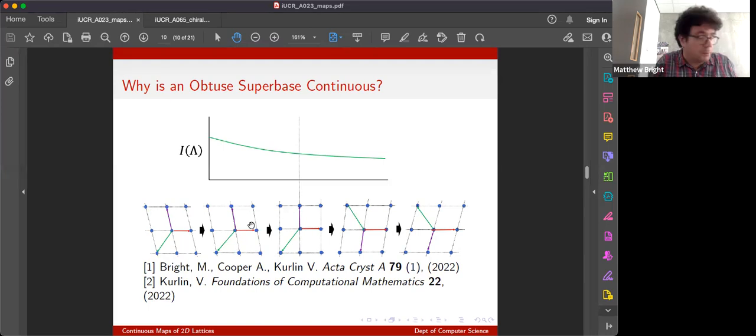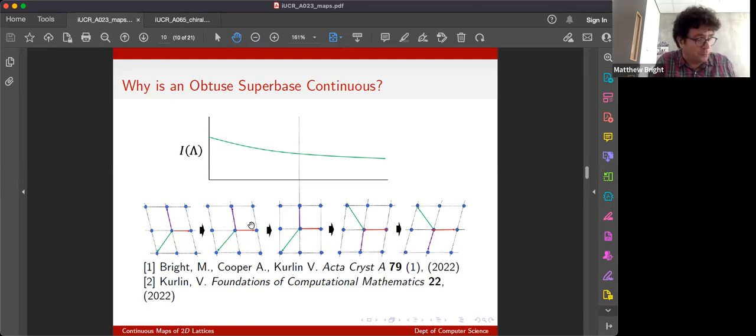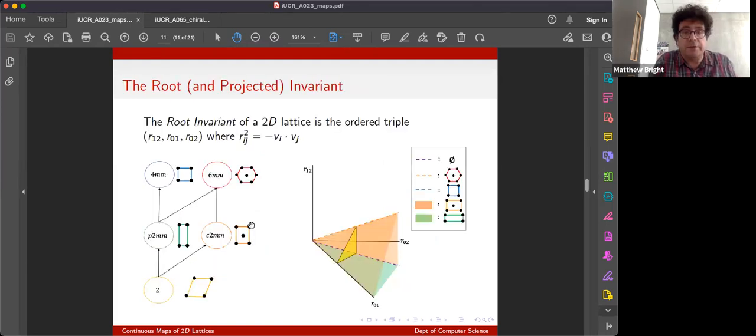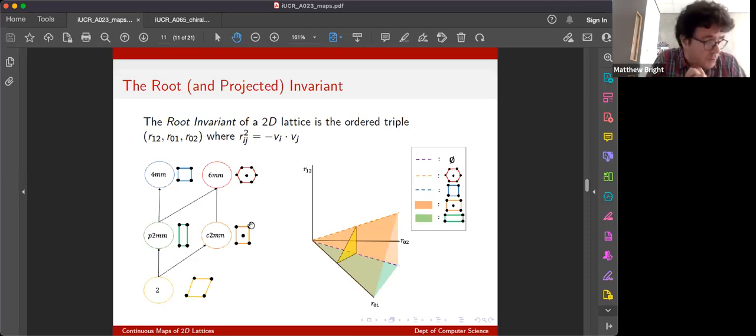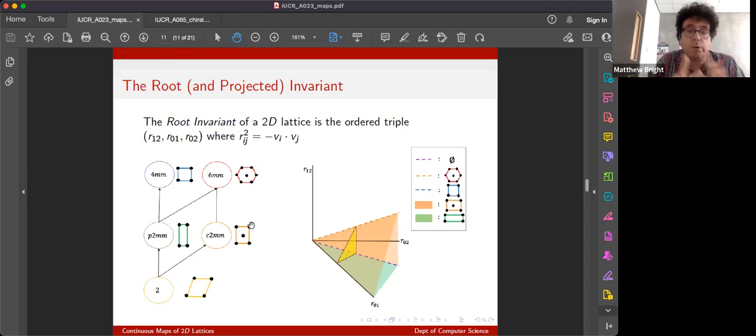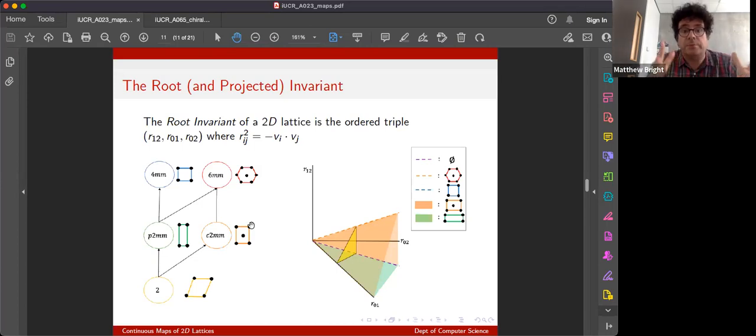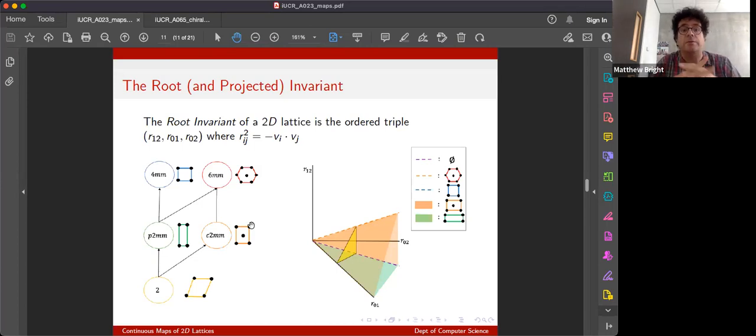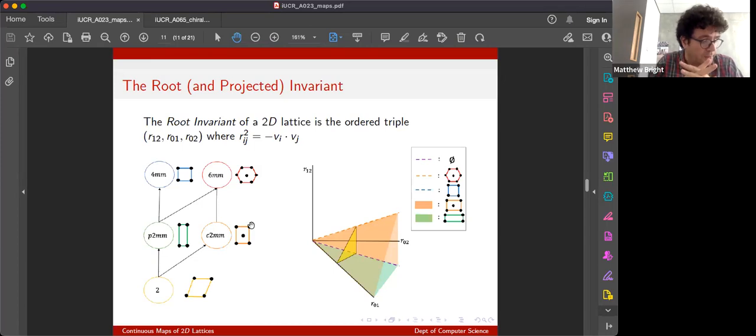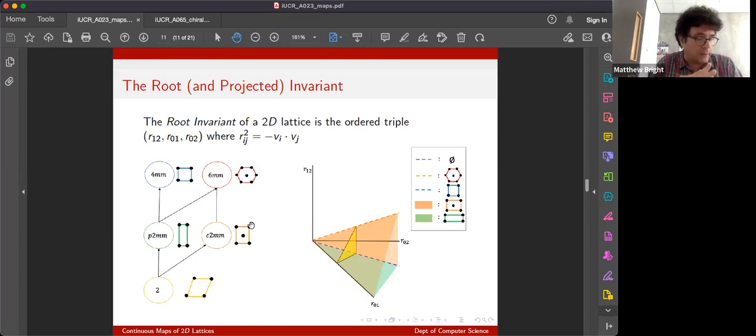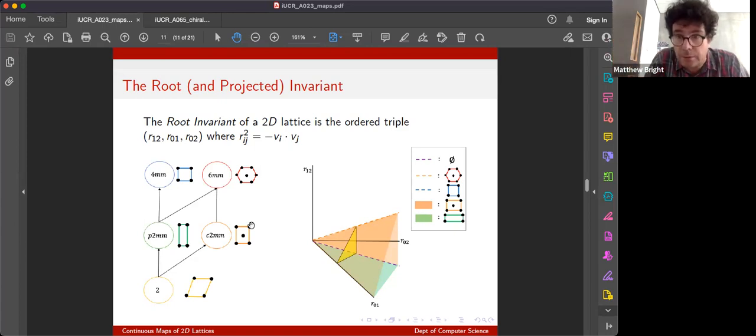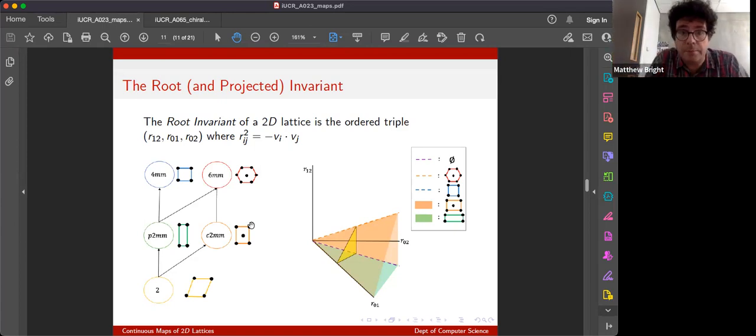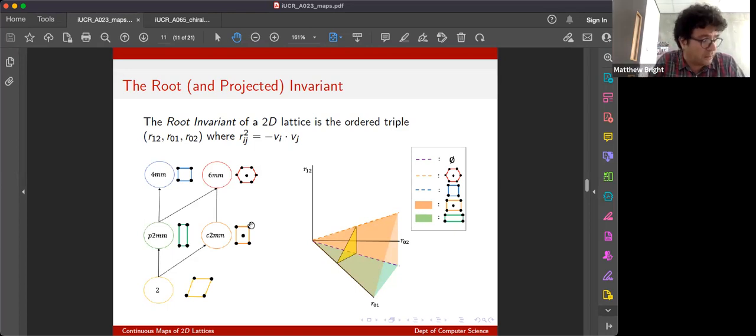So we want to take something that arises from the parameters of all three and is invariant under permutation, which obviously you simply order, you take the ordered triple perhaps of the inner product. The inner product is built up from length and angle, so it's isometry invariant. And if we put them in order, it's kind of impermeable. It doesn't notice permutations, it stays where it is. So that's an isometry invariant.